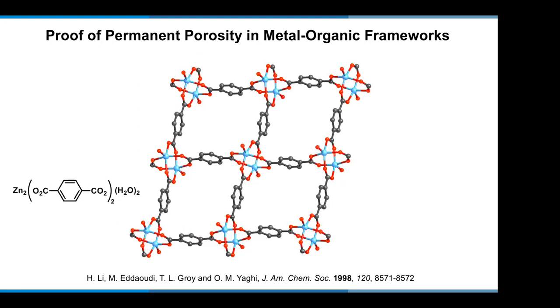So from my training, of course, as an inorganic chemist, a carboxylate is very good at aggregating metals. And so we find the reaction conditions that would allow you to make this paddle wheel. And therefore linked, in this case, zinc, but also copper two, could be linked by these carboxylates to give a chelating system and a cluster. This is the so-called paddle wheel cluster. And this clustering then allows you to make an extended, in this case, a square grid.